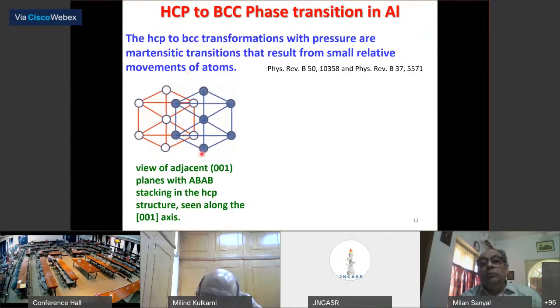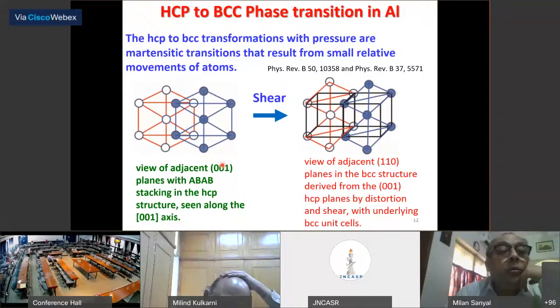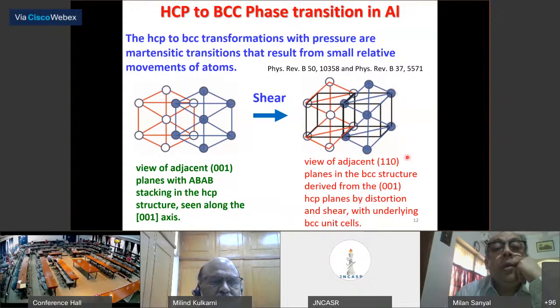So basically what happens here is the HCP to BCC transition. Why are you going to an open structure? The reason is that when you have an HCP ABAB structure along the 001 direction, a slight shear force can move the atoms to form a BCC structure. And this is now the 110 of the BCC. It's a beautiful martensitic transition which is happening in the system, and that is the reason why a BCC would be stabilized in the system.